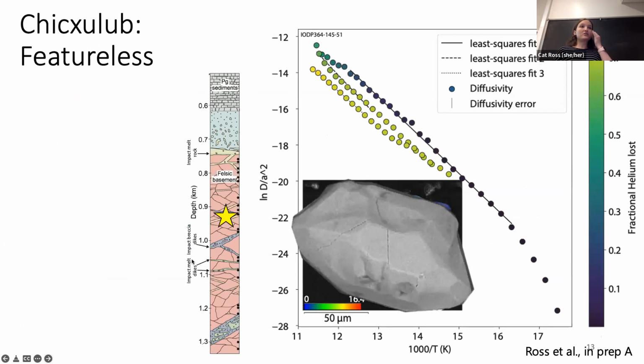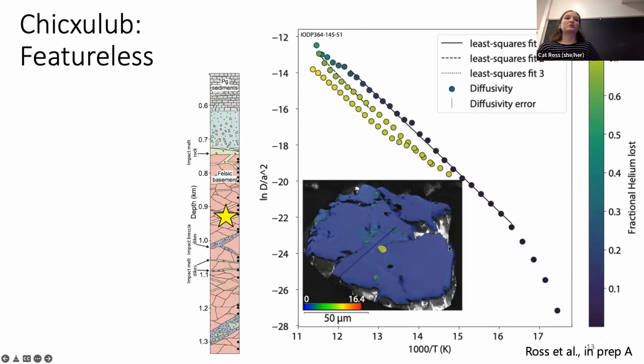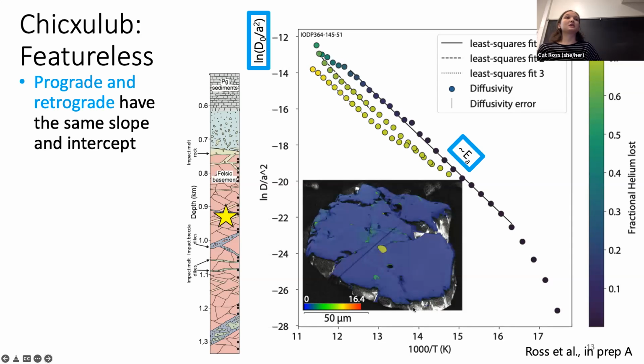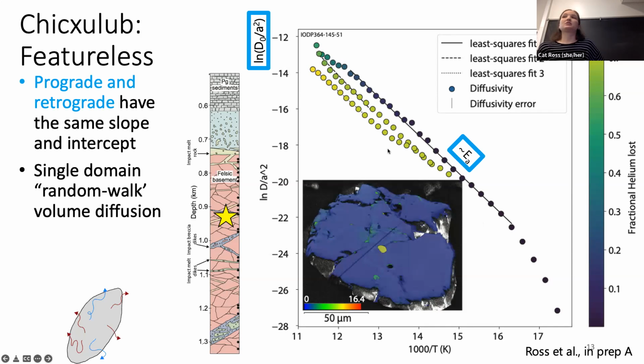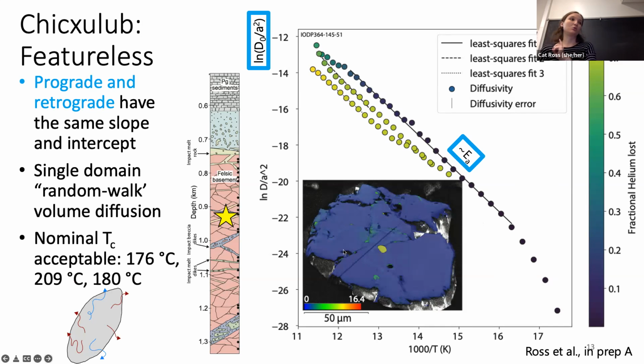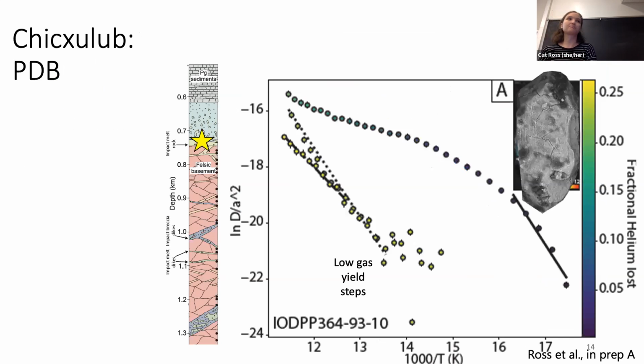So I'll quickly run through some of these Arrhenius plots. You can see this is a featureless grain from the Chicxulub, and that's confirmed with the EBSD image. We have the same slope for the prograde and the retrograde paths, and so this is indicative of one single domain. You're diffusing from the entire grain all at once. And our closure temperatures are within the accepted range, so it should be around 200 degrees Celsius.